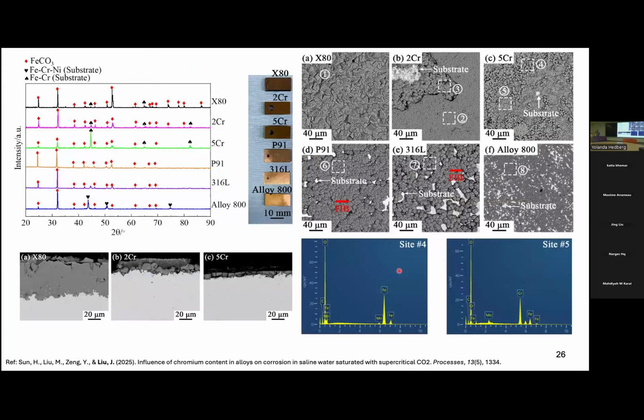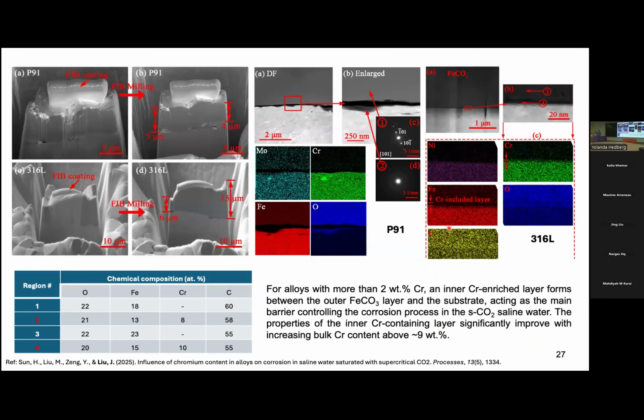Now, after this, we did just regular characterization, and then we got rejected. The story doesn't change at all. We got rejected. We added TEM, we got accepted. So you see how annoying they are. So why P91, why starting at P91 it works, is if you look at the number 2 here for P91 and the number 4 here for stainless steel, they form an intermediate chromium-rich layer.